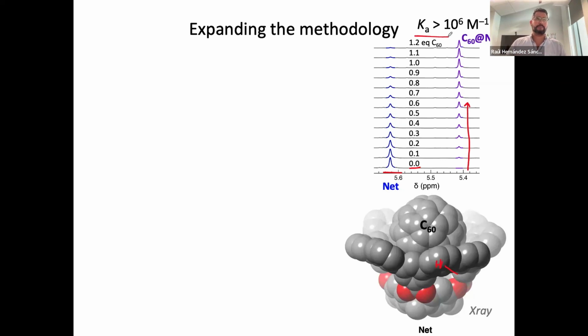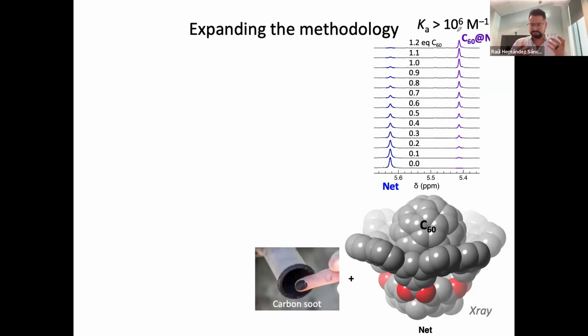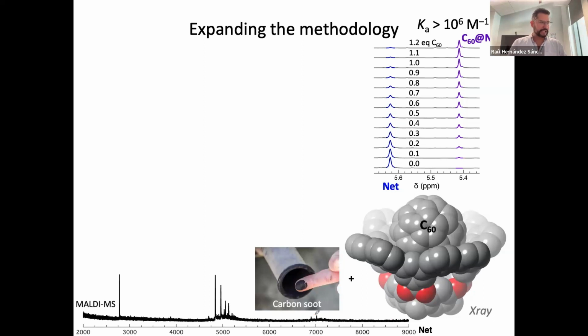Well, not here. And in fact, based on these experiments done via NMR, we know that the association constant is in excess of 10 to the 6 per molar. So when we got these results, we were thinking, how can we take advantage of these numbers, right? So we started thinking, well, carbon soot. I mean, carbon soot is essentially just partially burned carbon, right? The leftover. You're seeing that in that picture, right? And so we thought, what if we mix this net in a solvent plus carbon soot? Will we be able to extract fullerenes from carbon soot, which in another way to say it is from garbage, right?